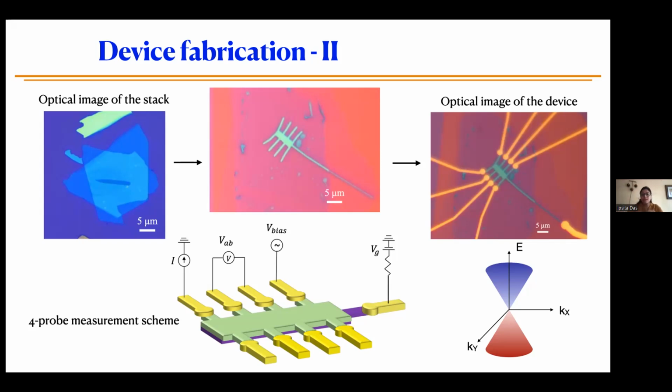However, in twisted bilayer graphene you have a flat band, but due to the strong interaction you will also have small gap openings. So as you tune the carrier density, you see some metallic regions and then some insulating regions, and within the flat band you have highly resistive or low resistive states, because you are basically tuning through different densities of states. Okay, thanks.